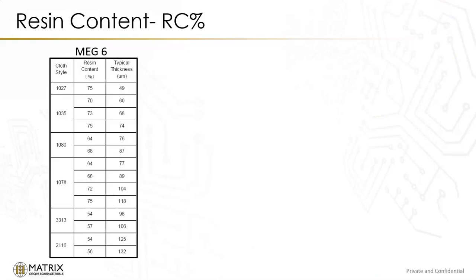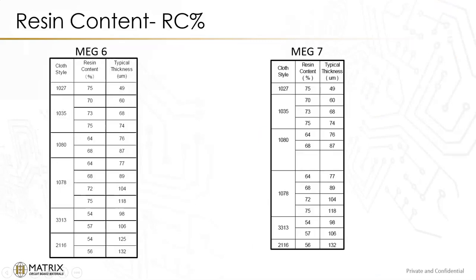But what we also have to understand is the resin content. So typically if you're looking at a lineup and you're looking at a stack up, we want a certain thickness, and so we're able to go down the line. So we have a 1035, and then we have a resin content that's associated with that, and then a typical thickness. And this is just thickness between copper planes. And between Meg 6 E-glass and Meg 7 E-glass, it's basically the same. So if we have a 75% 1035, that gives us 74 microns of thickness, and the same thing for the Meg 7. We've got 74 microns of thickness, almost 3 mils.